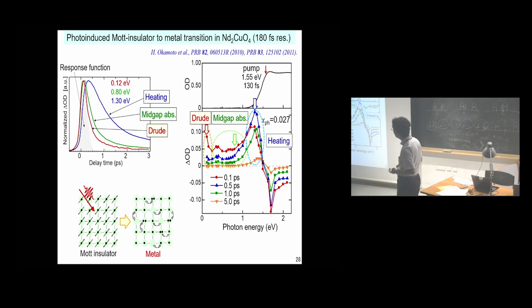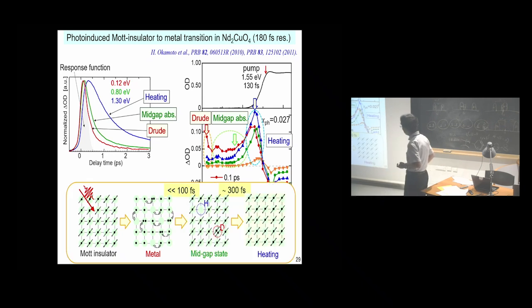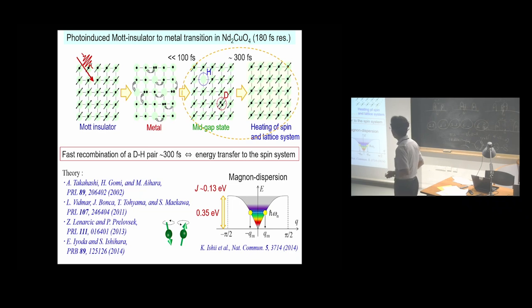Detailed analysis of time evolutions of absorption changes at these three probe energies revealed that the decay of the metallic state occurs very fast. That is much faster than the time resolution. And the residual holons and doublons also decay very fast. Its decay time is about 300 femtoseconds. What is the mechanism of this ultrafast decay? Several theoretical studies suggested that the fast recombination of a doublon-holon pair in this region is possible via the energy transfer to the spin systems. In this compound, the exchange interaction J is about 0.13 eV, and magnon dispersion exceeds 0.3 eV. So a magnon is a good energy receiver.